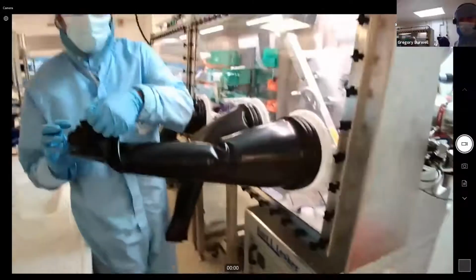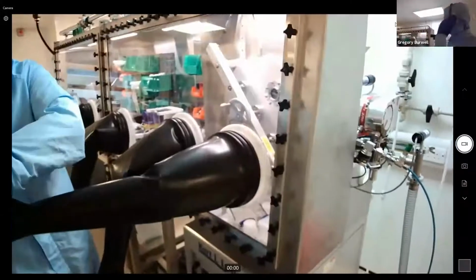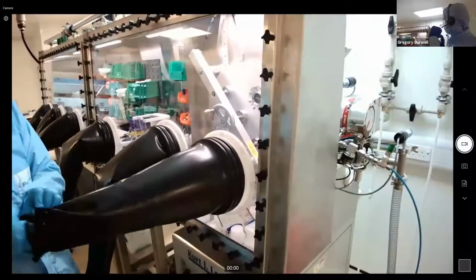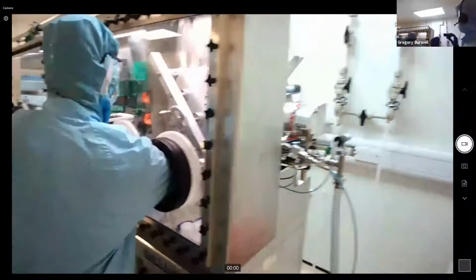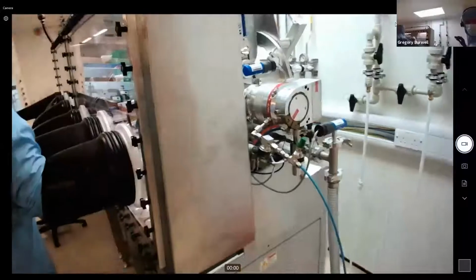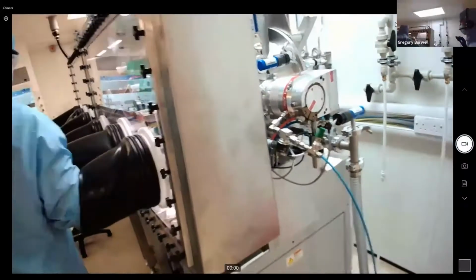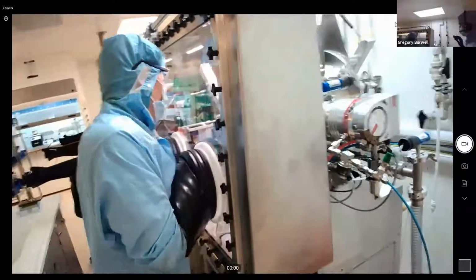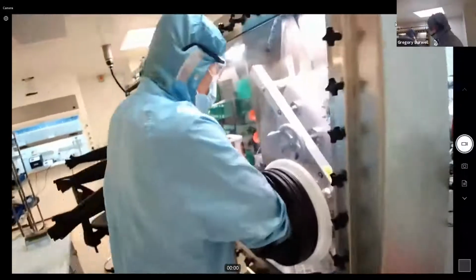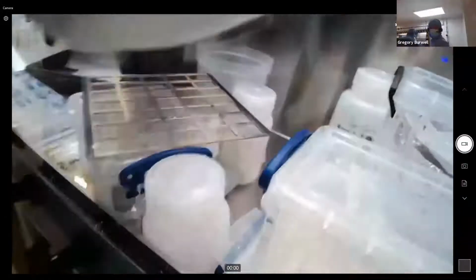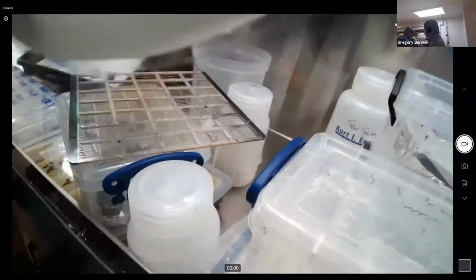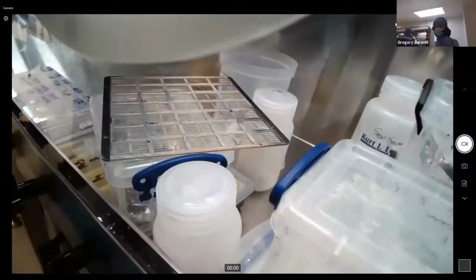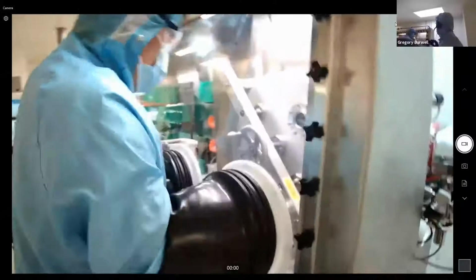And I think next we'd like to show you how we put the top electrode on these cells. What we're going to use is a thermal evaporation system. And this is a system that's capable of pumping down to very low pressures, to the 10^-7 torr kind of range. It achieves that using a turbomolecular pump, you can see on the side here. And Wei is going to be loading up the evaporator. If I show you down here, what we can see is a shadow mask. So this will help us create different pixels on the substrate that Wei just cast the film on.